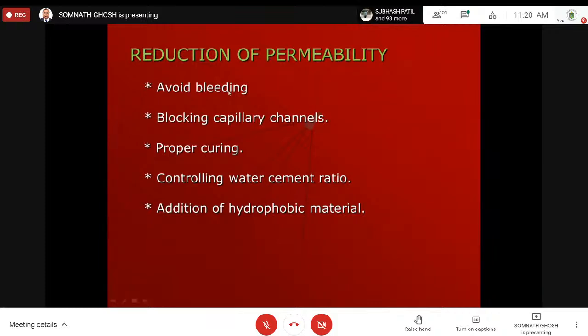Now you have to avoid bleeding, block the capillary channels, and provide proper curing, which is very, very important. Controlling the water-cement ratio is very, very important. If you don't control the water-cement ratio, it will be a porous concrete. No use of it. You can also provide additional hydrophobic materials just to reduce the permeability, right?